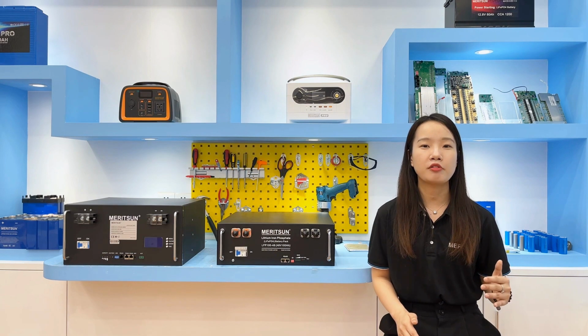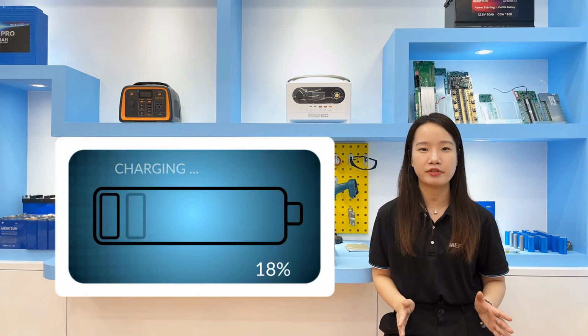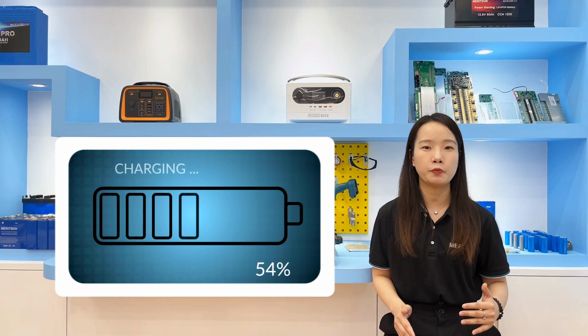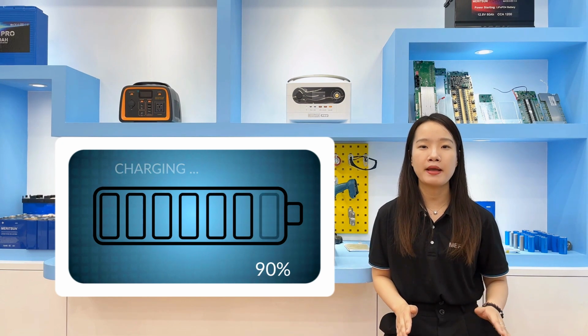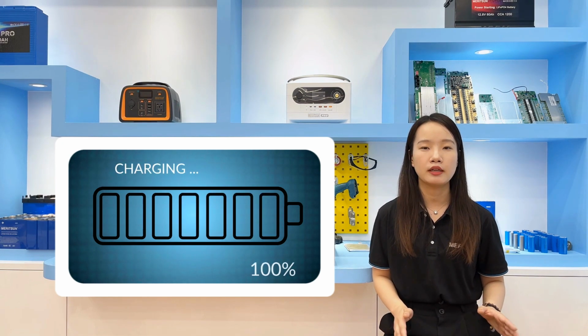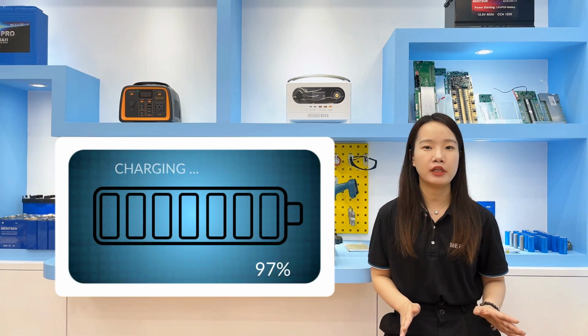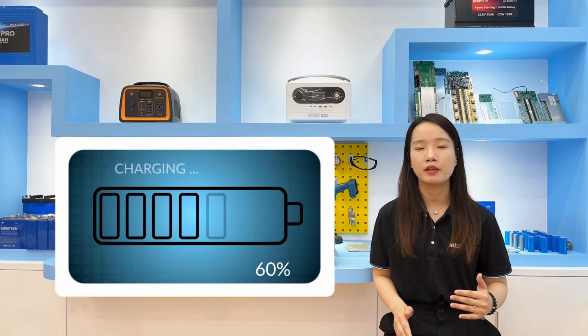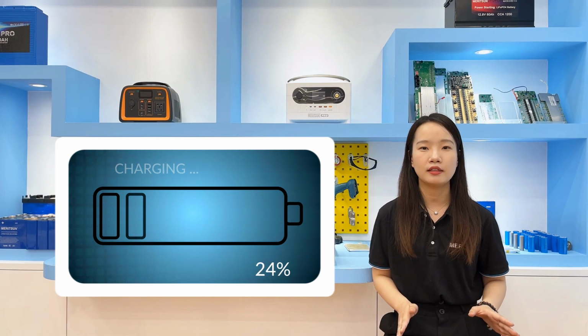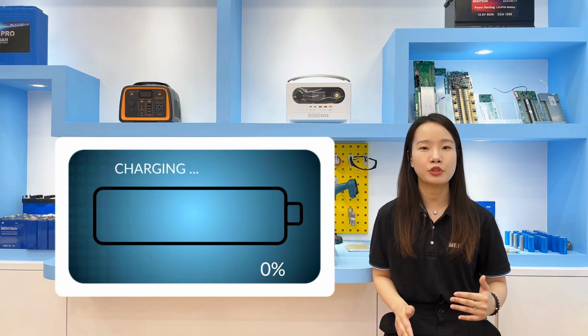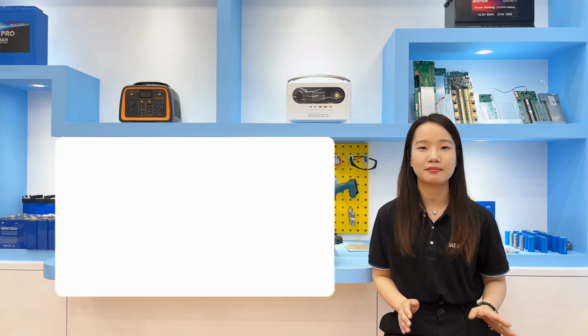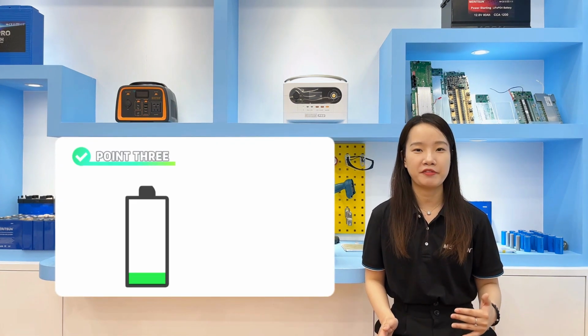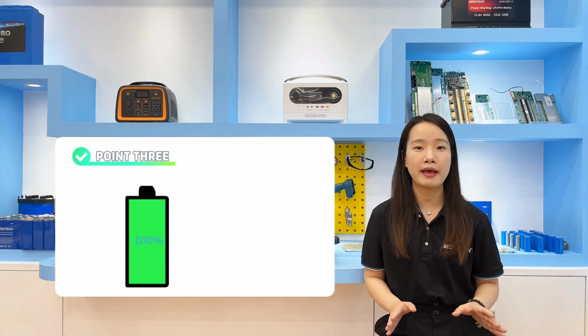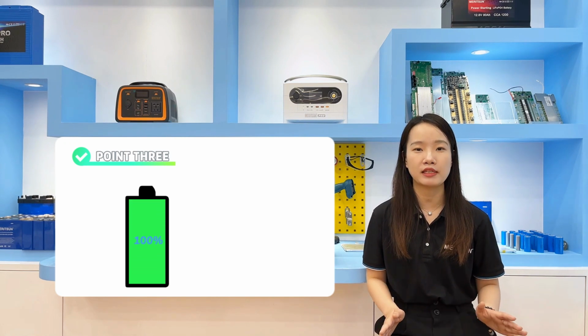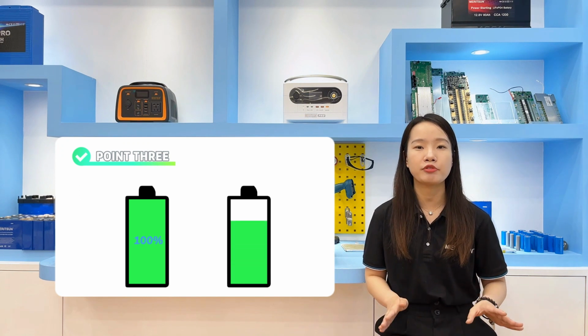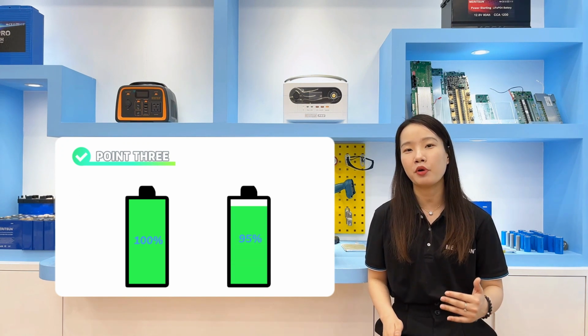Fully charged, the resulting high voltage increases the capacity of the batteries, but puts stress on the electrode, which expands the cell to allow all ions to penetrate. Conversely, while the battery is fully discharged, to 2.7 volts per cell, a chemical reaction occurs inside, making the electrode oxidize, shrink, and change, and the battery ages faster. The lithium batteries have no memory effect. So even if you have not charged the battery to 100%, it has no effect. In the long run, if you charge the battery to 95% SOC, it can prolong the battery life.